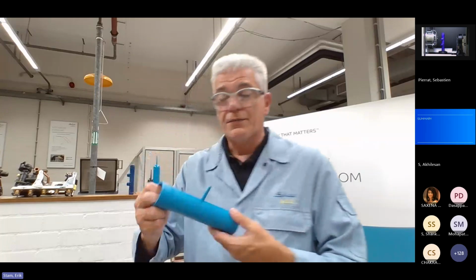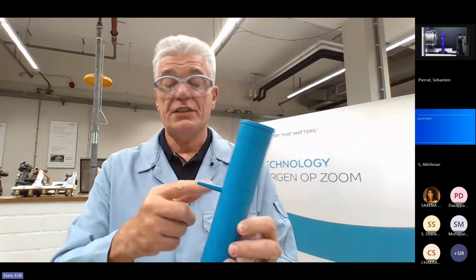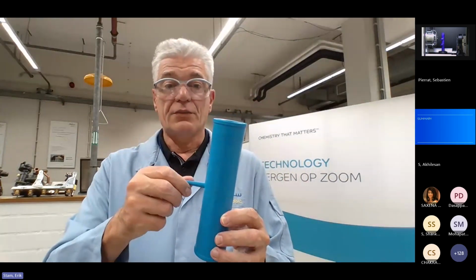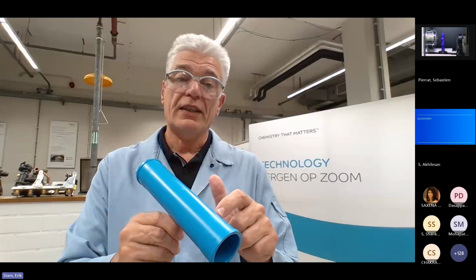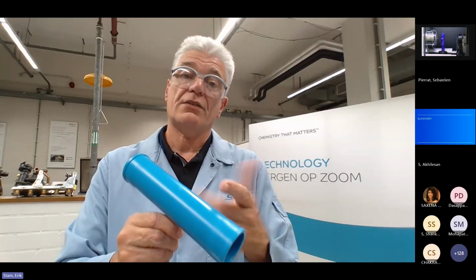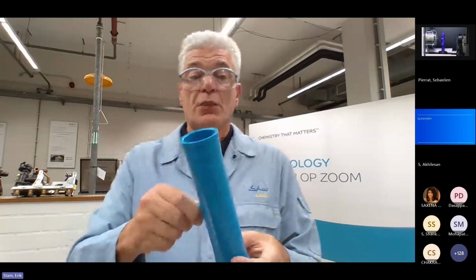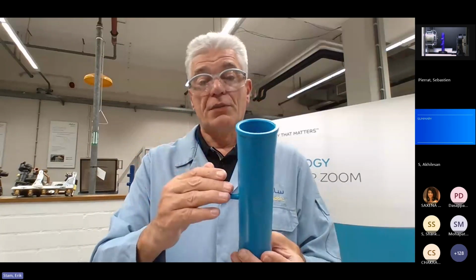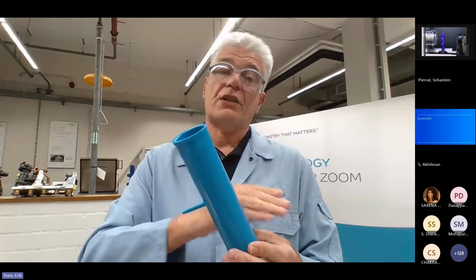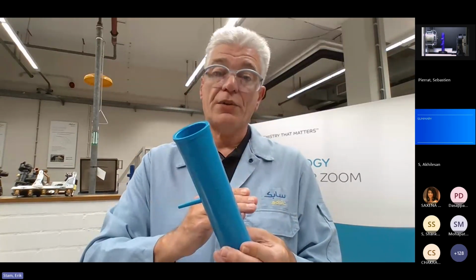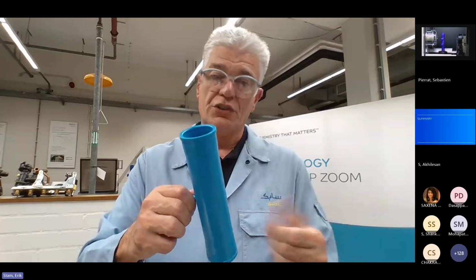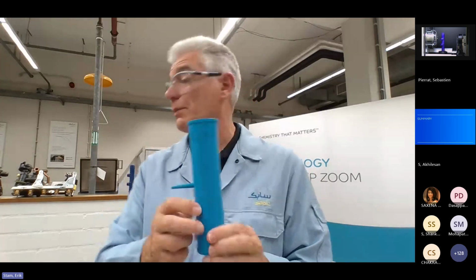What we also have is a pressure vessel which is injection molded from the side. And we do this because you generate a weld line. That's a weak spot in many cases for materials in the application. But in this case, because we mold it from the side, it means that the fibers are orientated more in a favorable direction, so also giving more strength compared to the top-gated sample.